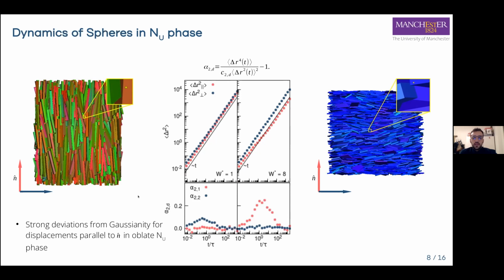We also computed the non-Gaussian parameter, and we observed in this case for the spheres a more prominent deviation from the expected Gaussian-like distribution of particle displacement for the diffusion of hard spherical tracers in the direction parallel to the nematic director in oblate nematic phases. And we think that this occurs most likely due to the higher number of collisions that the hard spheres may have with oblate particles with respect to prolate particles, due to their higher extent in space, which is for oblate cuboids rather than prolate cuboids.